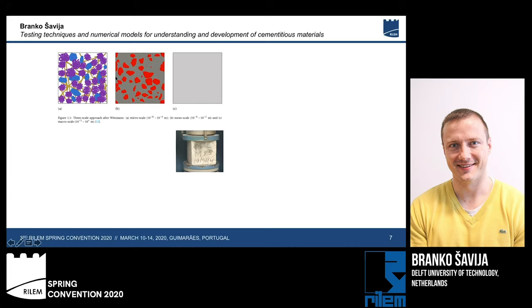If we go one scale lower, to a millimeter to centimeter scale, we see concrete not as homogeneous anymore, but as an assembly of aggregates suspended in a hardened cement paste. And at this scale, we can still perform some tests. It becomes a bit more difficult, but with some effort, we can still do it. We can understand how aggregates and heterogeneities influence the mechanical properties, the transport properties, and so on of cementitious materials.